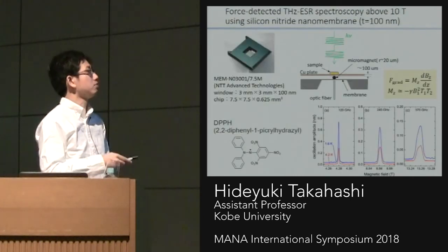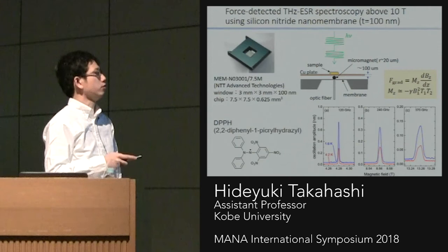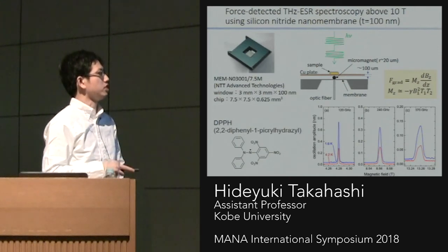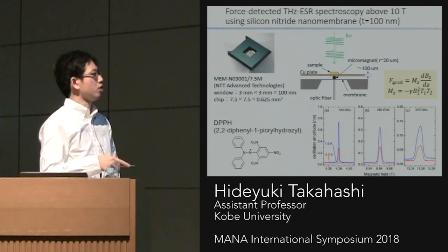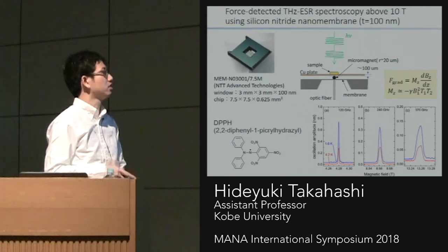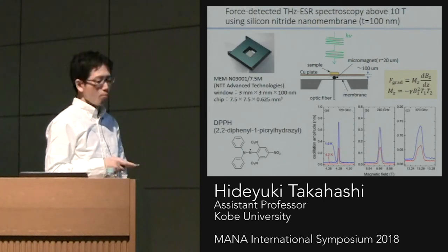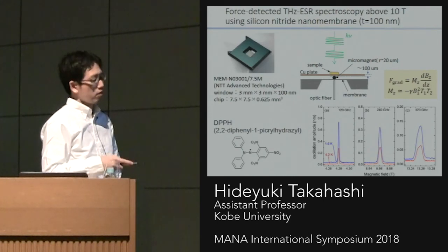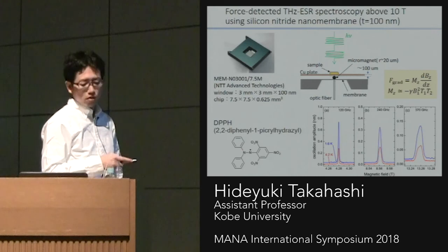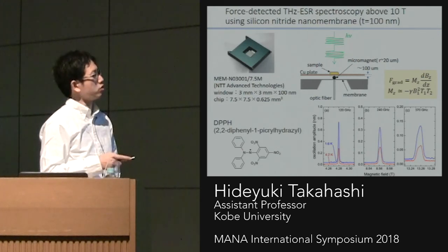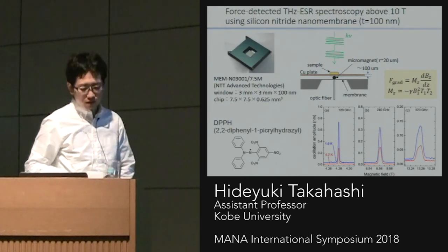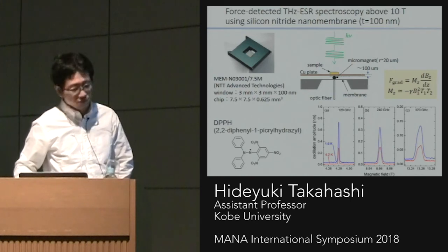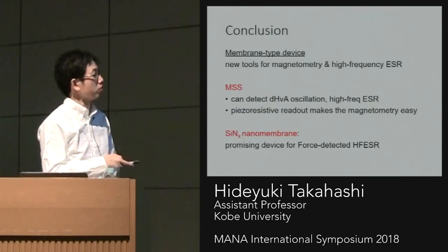But using this method, we successfully obtained the ESR spectrum at very high magnetic field. We succeeded in this technique up to 15 Tesla. So this is also a promising technique of high frequency electron spin resonance measurement. Sorry for going over time, but I should conclude.